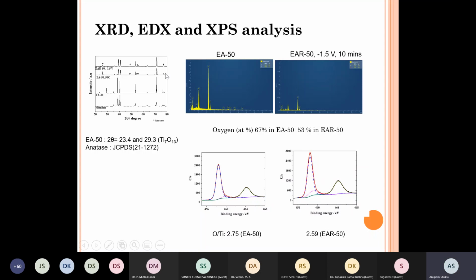Then again some characterization. XRD to see that titanium is found, and what other phases are found. And then some EDX to see what the oxygen is here, and then of course XPS, because that will give a much better understanding of whether we have oxygenation here. One of the things with titanium oxide is that if the oxygen to titanium ratio is reduced, then the conductivity increases. These are known as defects. If these are oxygen deficiency defects, then they increase the electronic conductivity. So this is what is shown here. The O to Ti ratio was 2.75 in the unreduced anodized electrode, and when it is reduced, it goes down to 2.59, which is a substantial reduction.